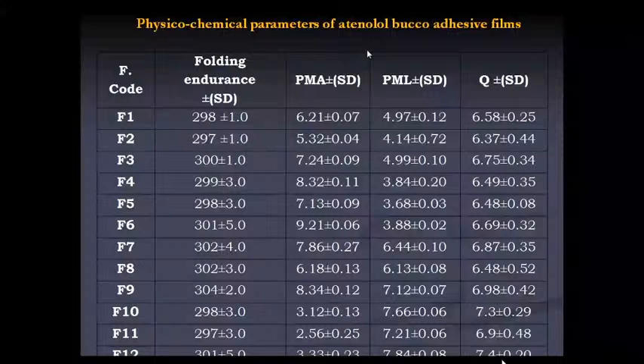For that, we need to do this test using aluminum chloride and calcium chloride in the desiccator. We need to keep it for 3 days. Again, before keeping it inside the desiccator, you need to check the initial weight. After that, you need to check the final weight. Then, using the formula, you can calculate the percentage of moisture absorption and percentage of moisture loss. So these are all the important tests you need to do.